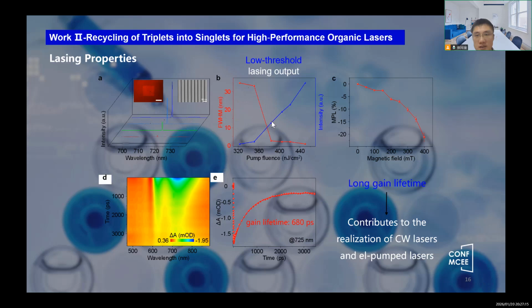The decrease in laser intensity with the increasing magnetic field strength indicates that the singlet excitons generated by the triplet upconversion process participate in the stimulated emission process. Further transient absorption characterization shows a longer gain lifetime, which is conducive to the realization of continuous wave lasers and electrically pumped lasers.